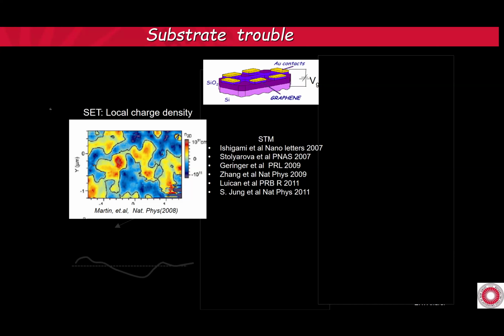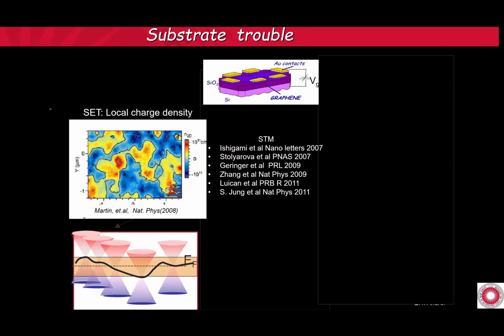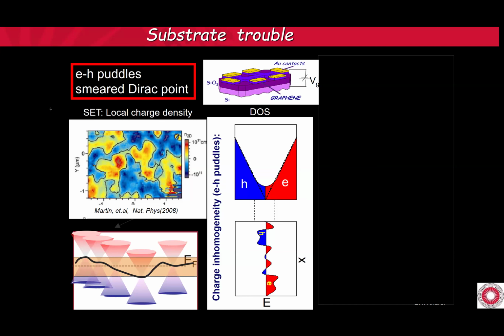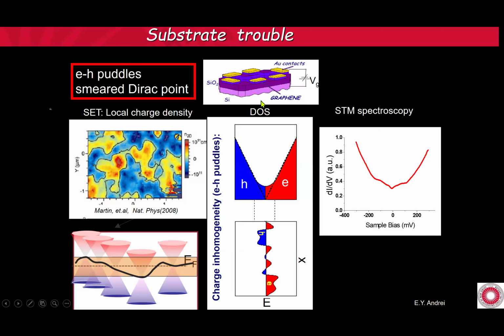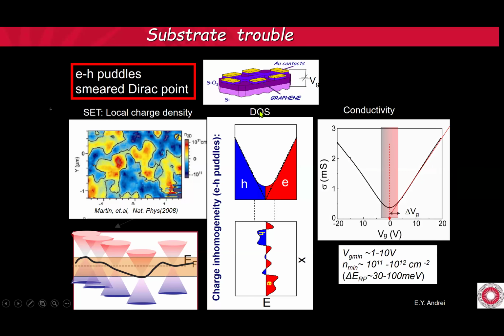And here, as many people have shown with many techniques, this is an example from Amir Yacobi's data with a single electron transistor, and you see you have huge modulations in the local density of states. What this means is that your Dirac cone is riding on this random potential, and when you do a macroscopic measurement, you actually average over this whole thing, so you smear out all the interesting physics that happens at low energies like this. So you round off your density of states, which should be linear, and when you do STM, you completely lose whatever is going on at the Dirac point, and the same happens in transport. Okay, so one has to be very careful about that.